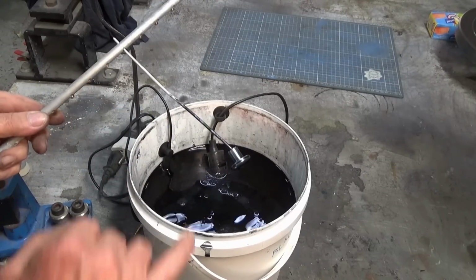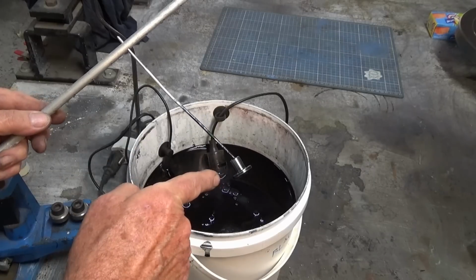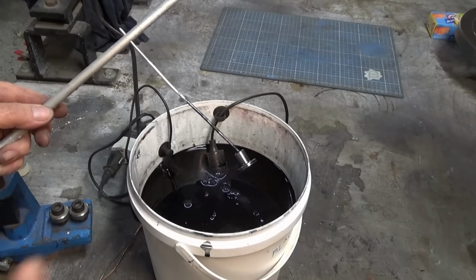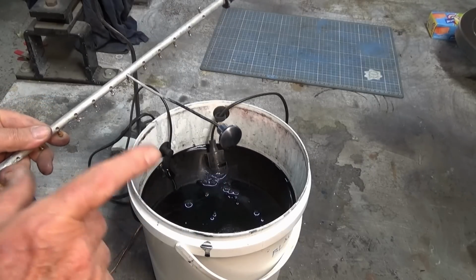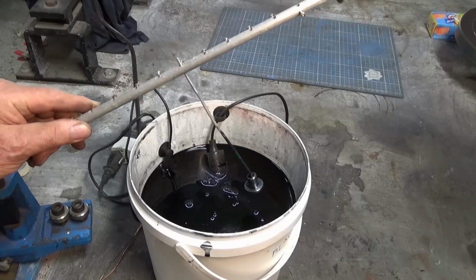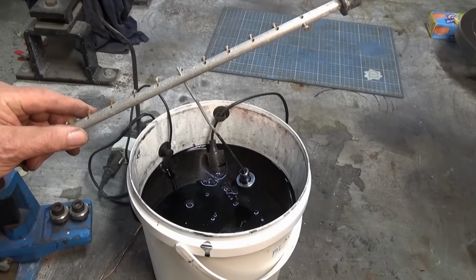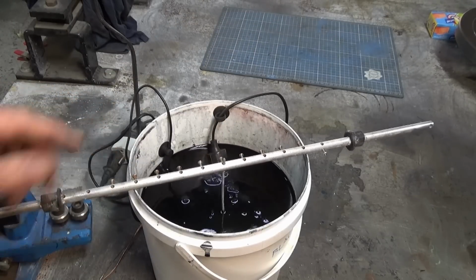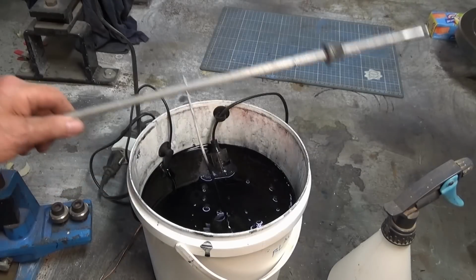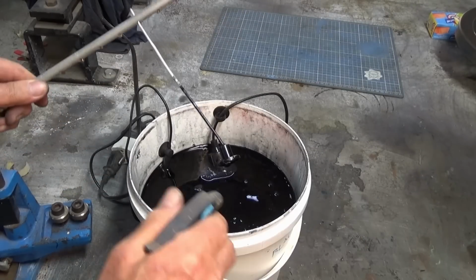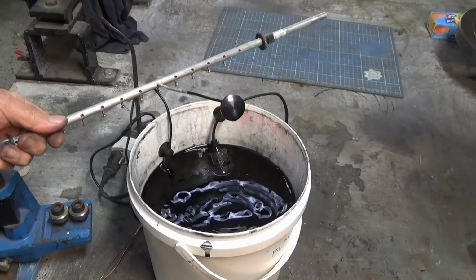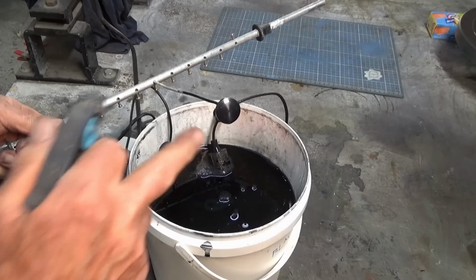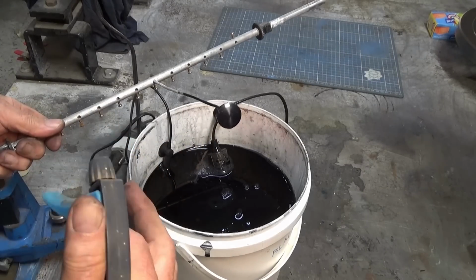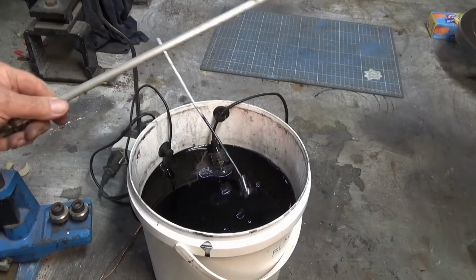Now often you see people on YouTube and they'll pull a part out after about 2 seconds and it looks like it's completely black. I'm here to tell you that almost never happens. This might take up to 15 to 20 minutes to take up that dye. Alright, that's been about 3 to 4 minutes, and you see it is starting to turn black, but it needs to be in there a lot longer to go that really dark, uniform black.